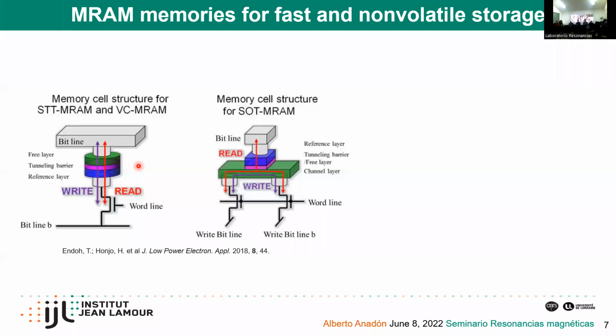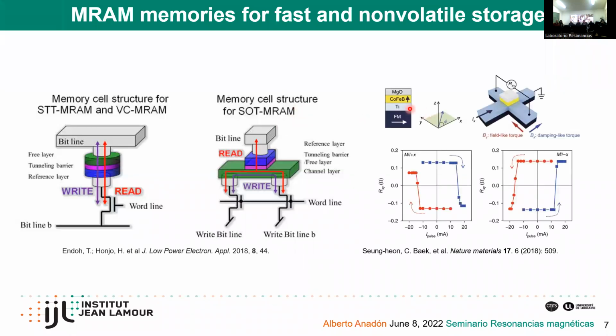And one way to try to overcome this is the use of spin-orbit torque. Spin-orbit torque comes from the spin-orbit interaction that I have discussed before. What we can do is use spin accumulations generated by electrical currents in materials or systems with spin-orbit coupling to be able to switch the magnetization of a ferromagnet. And with this, we can create this kind of memories. There is mostly one big limitation. Well, there would be two, but one of the most important is the fact that to have an efficient switching with a spin-orbit torque, you normally need an in-plane magnetic field to facilitate this switching. But there are already some advances that we have been discussing in literature to overcome this and to have field-free switching. The other disadvantage would be that the electric current needed to switch with a spin-orbit torque is also high, and it should be much smaller.